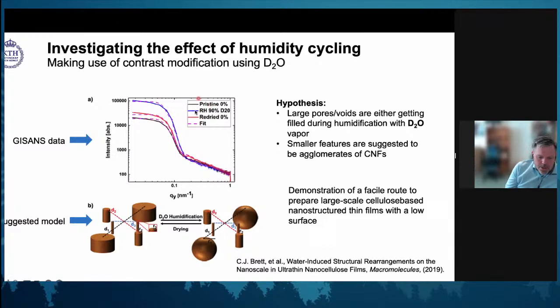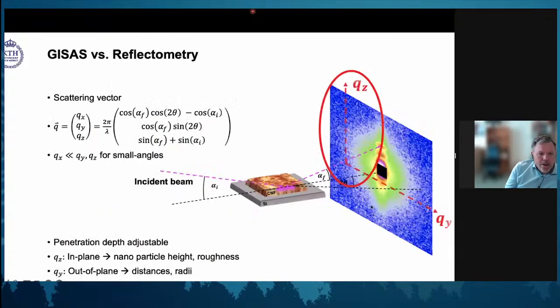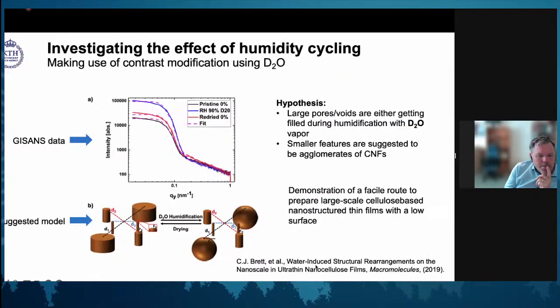So with the pristine films dry, we get a scattering. And in this case, we are not talking about the scattering in this direction, we're talking still about this direction. So we're doing exactly the same as with X-rays. And by doing this, we can start to figure out what happens when water enters into the film.